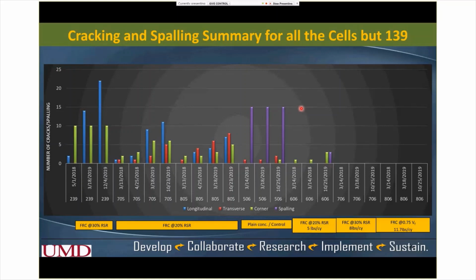So as far as fatigue crack quantification is concerned, cells 506 through 806, those are the cells where we varied the fiber doses, but those slabs, in terms of cracking, are performing really well. So we still could not quantify the fiber's contribution, or what dose of fiber is good, or what residual strength ratio or residual strength would be good.